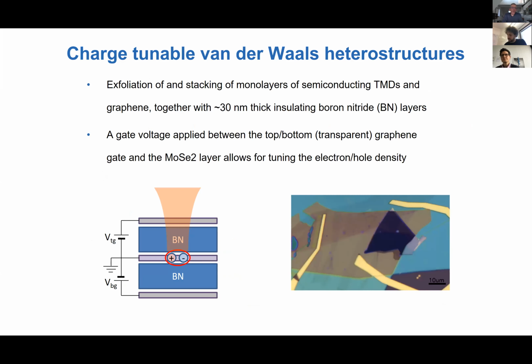Okay, so now, after this very brief introduction, I'd like to talk about the devices that we use, and these are charge tunable van der Waals heterostructures. Maybe van der Waals heterostructure terminology is a bit of an overkill, because basically I will tell you about a monolayer of TMD, in our case molybdenum diselenide, sandwiched in between boron nitride layers. And boron nitride is another 2D material that is insulating. Okay, and then the graphene layers on top and below act as gate electrodes, which allow us to control the charging of the molybdenum diselenide layer. And here is a micrograph of a typical device that we have.